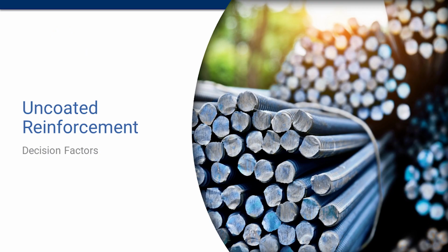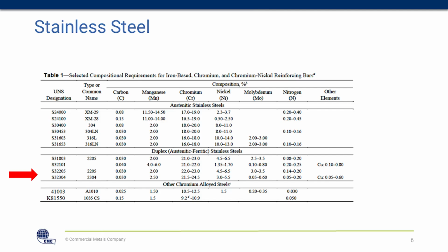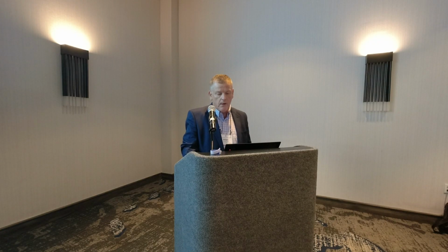So to get started with the uncoated material, this is just an AASHTO rebar table that shows the most common that we see. There's 2304, which contains up to about 24.5% of chrome and up to about 5.5% of nickel, and then the molybdenum is between 0.05 to 0.6 in steel chemistry.